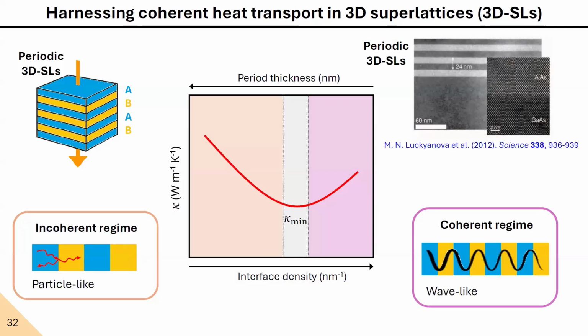So there are many experimental works that show this kind of trend and show a crossover from incoherent to coherent heat transport as we increase the interface density. This is, we decrease the period thickness. We make these constituent materials thinner and thinner, and in turn, when they are very thin, so high interface density, phonon transport is coherent. When they are thicker, we have a particle-like behavior and phonons mainly scatter at the interfaces.